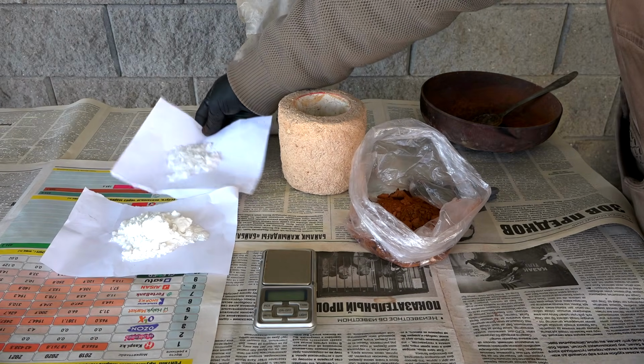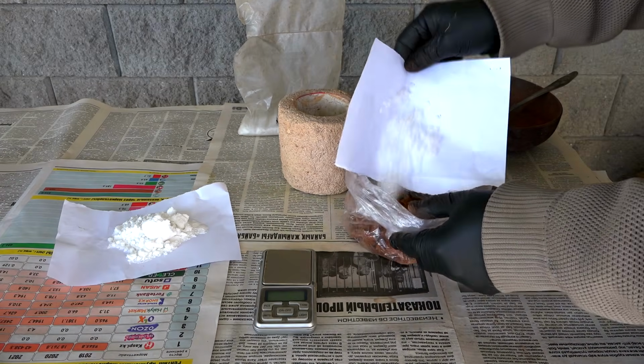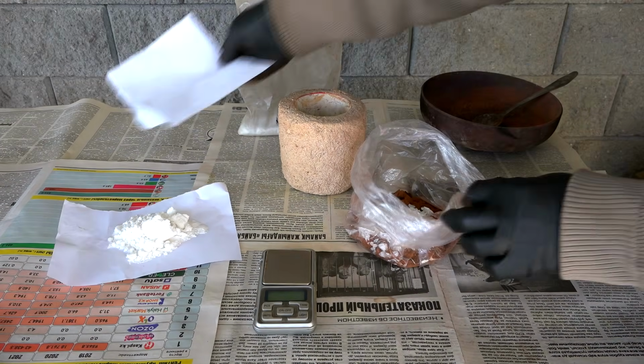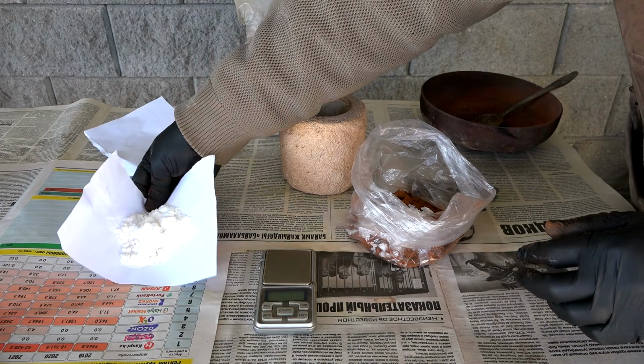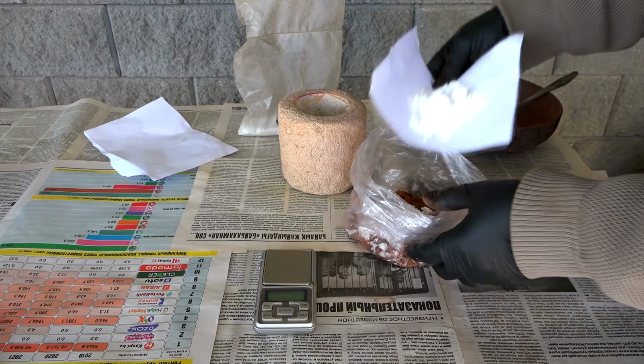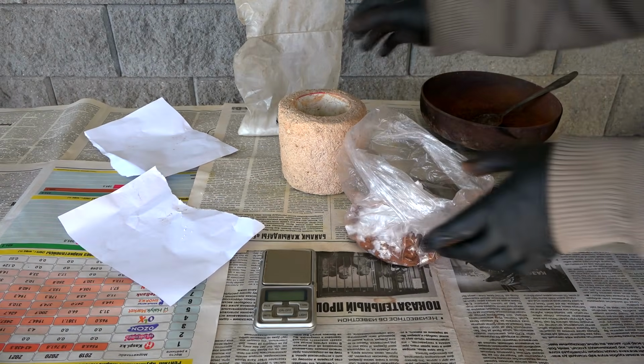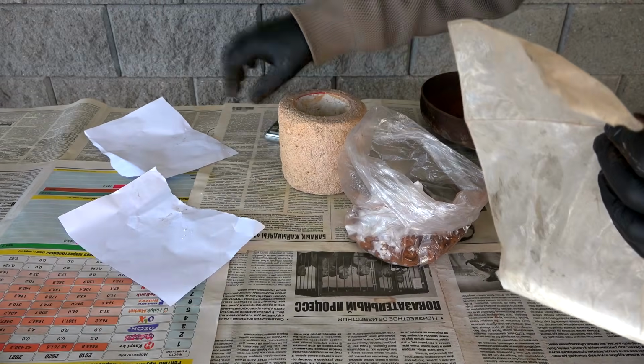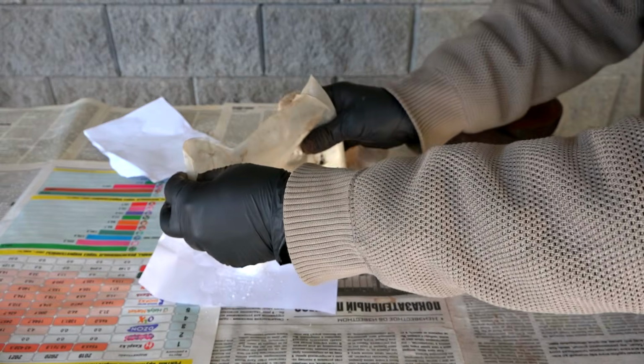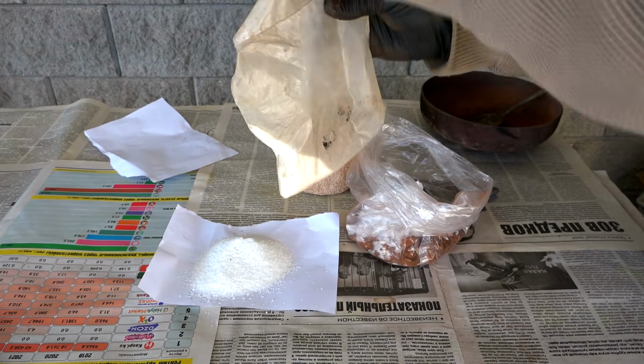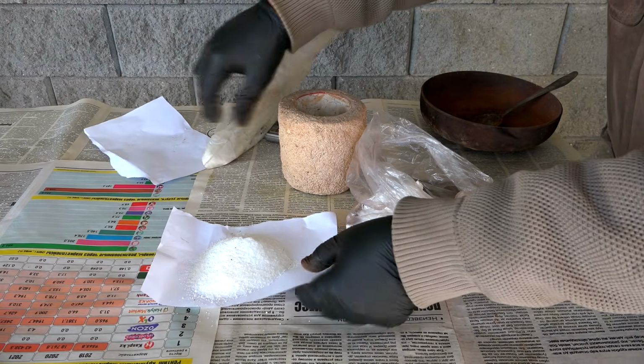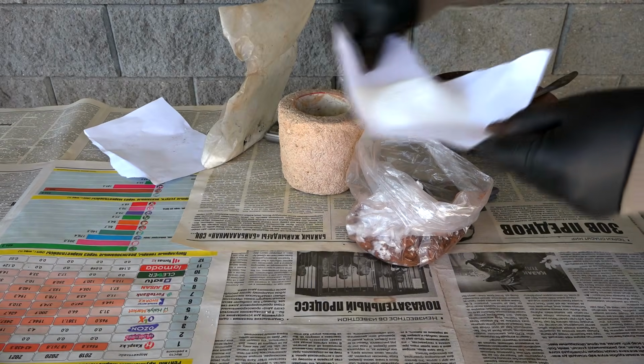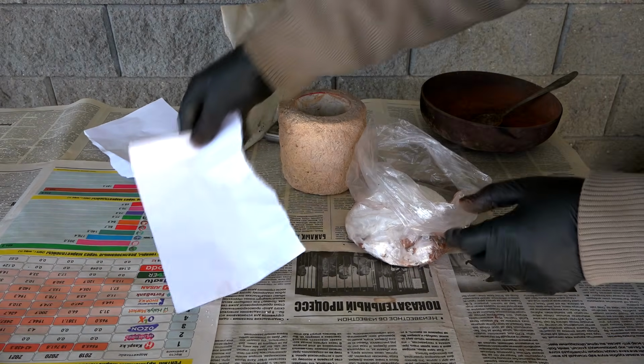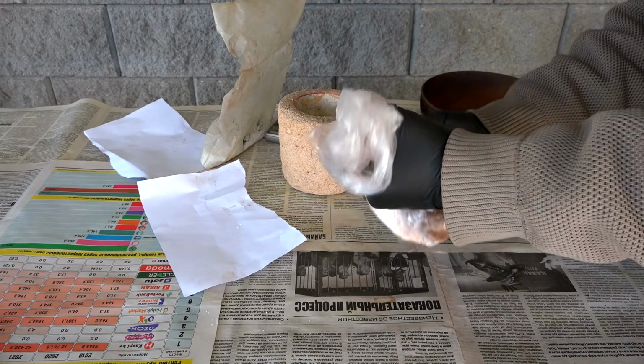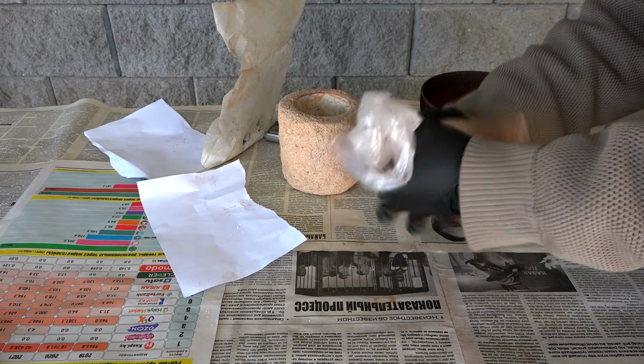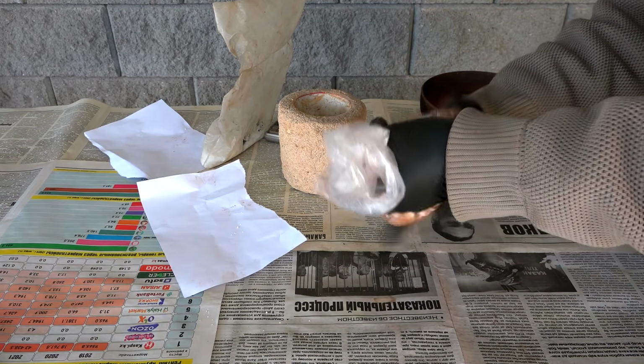It's time to add and mix the simple alkaline substances. First, I add sodium hydroxide, caustic soda, but be careful not to overdo it. Otherwise, the material will foam during heating. The second substance I add is sodium bicarbonate, baking soda, several times more than the first component. And finally, I add sodium tetraborate, borax. Using these three components, it's easy to fuse the flotation concentrate with the lead.